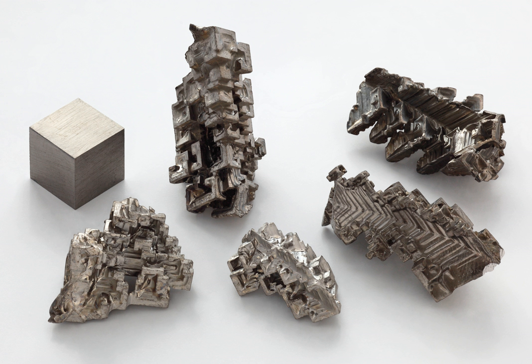Low-melting alloys, such as Bi-Cd-Pb-Sn alloy which melts at 70 degrees Celsius, are also used in automotive and aviation industries. Before deforming a thin-walled metal part, it is filled with a melt or covered with a thin layer of the alloy to reduce the chance of breaking. Then the alloy is removed by submerging the part in boiling water.